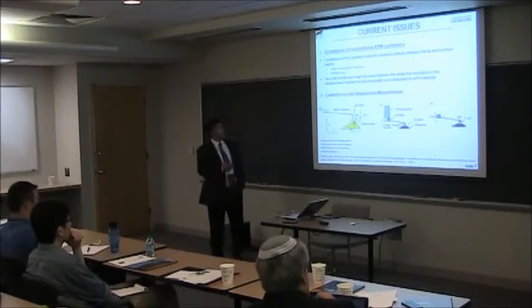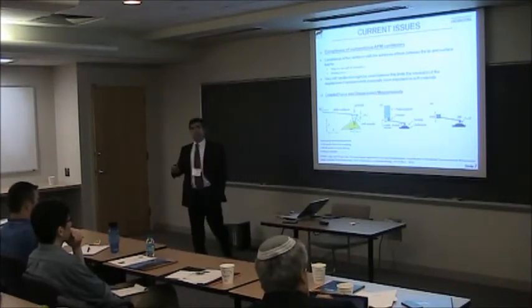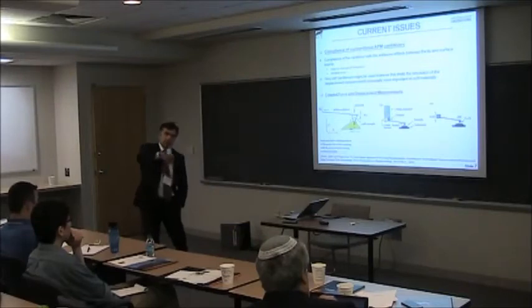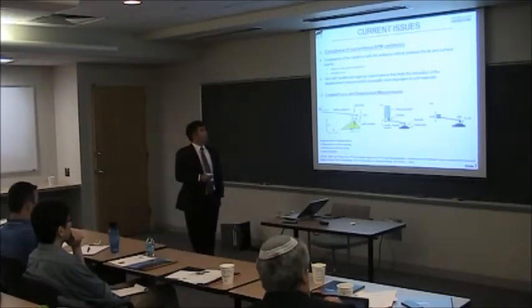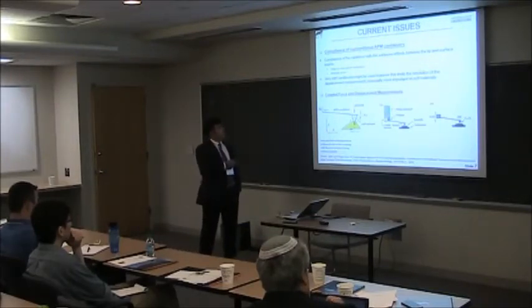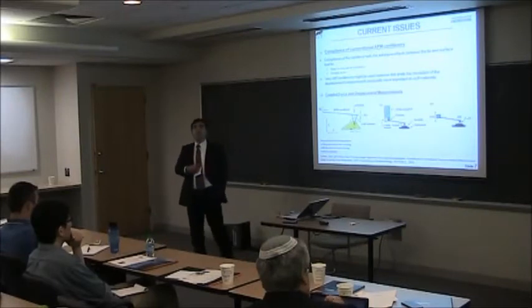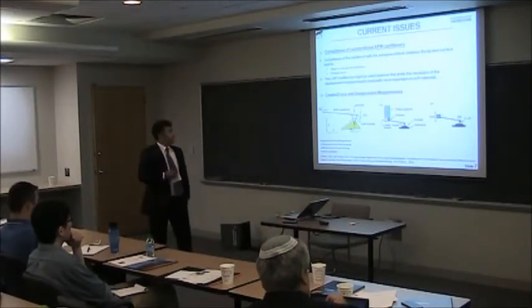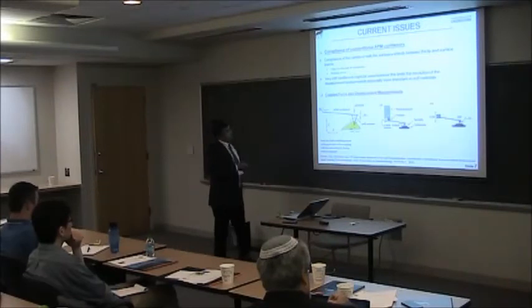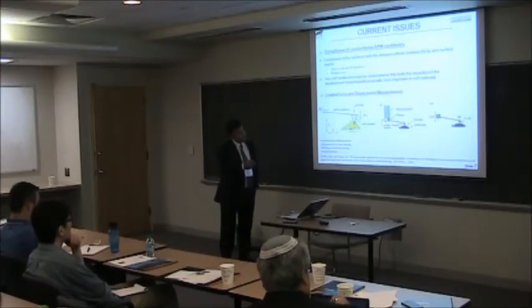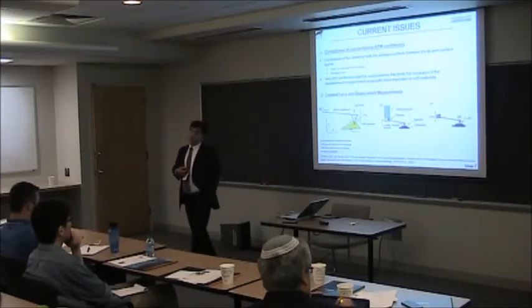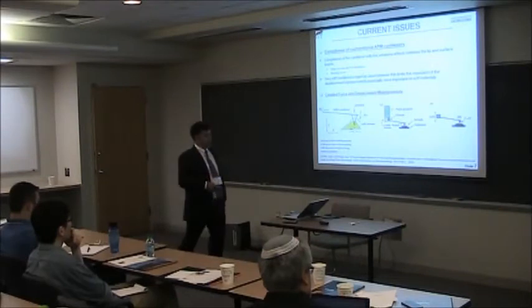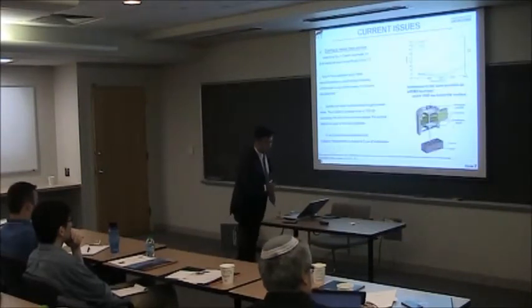And the main problem is snap-on and pull-off instabilities, where you touch and you release and you shake. Obviously, you have oscillation. Bending errors, definitely, if the AFM cantilever will bend. And another problem is that when you're pushing down, it's not just going down in this direction, it also moves in the other direction, which you don't necessarily count. So those are the things that are generally problematic in those probes.